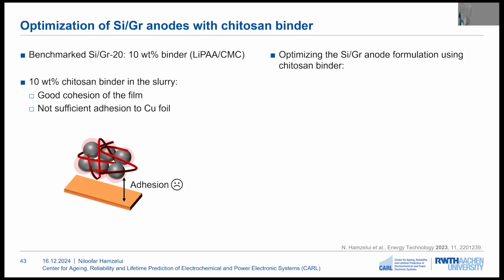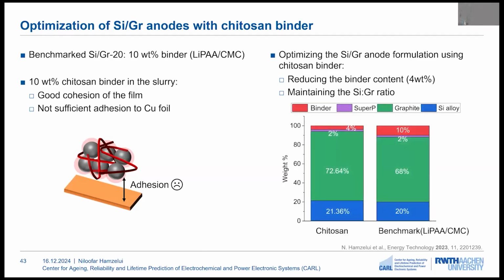Therefore, here we can see that by only changing one factor like the binder in the electrode, we need to further optimize the electrode formulation for this specific binder. And the optimization was done on the silicon graphite electrodes using chitosan binders, and different amounts of binders were investigated, and 4-weight% binder showed a balance between the cohesion of the electrode and adhesion to the copper foil, and the ratio between the silicon graphite active materials was maintained the same. So here we can see the slurry formulation using the chitosan binder with 4-weight% binder, and here we can see the benchmark lithium polyacrylic acid CMC binder.